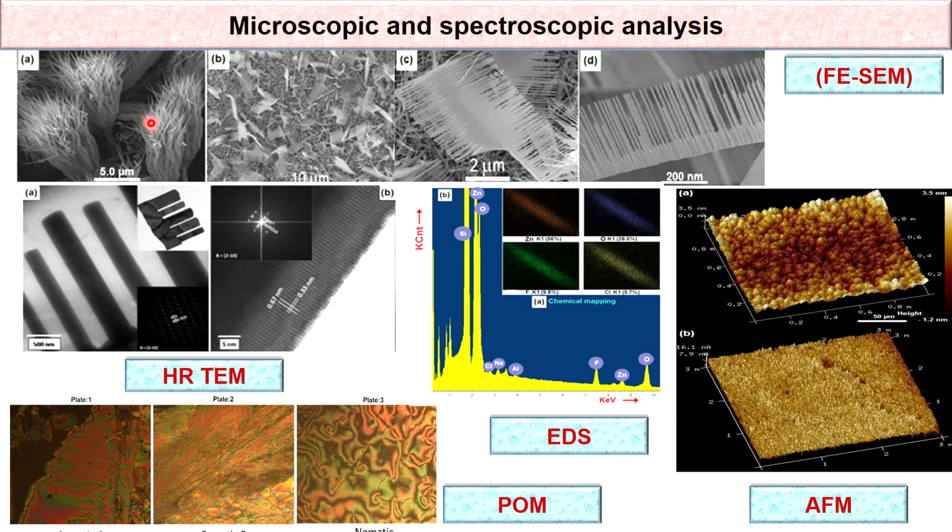And it also reveals that the nanoflower morphology is formed by the aggregation of multiple one-dimensional zinc oxide nanospikes. You can see that the nanospikes are emerging radially from the central part. And it is also seen that the nanoflowers do not possess uniform diameter. And this figure shows the formation of zinc oxide nanocomb. Nanocombs are evenly spread and grown abundantly over the surface.